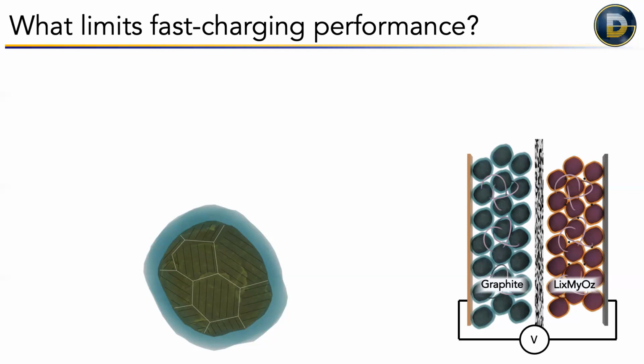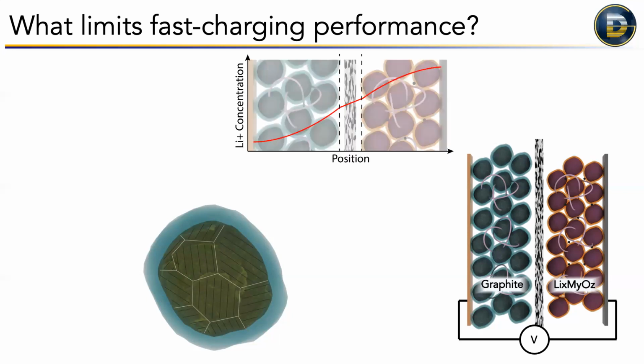But if we try to charge this too fast, essentially we can't put the lithium ions in fast enough, so they stack up and you form this concentration gradient across this porous structure. So you have more lithium ions at the surface of the graphite than deep in here. So then when you're charging your battery quickly, you're preferentially charging the surface of the graphite, and eventually the lithium ions stack up, the surface of the graphite gets totally full and crowded, and rather than just sit around, the lithium ions actually plate out as metallic lithium, and they form what's called a dendrite on the surface of the graphite.